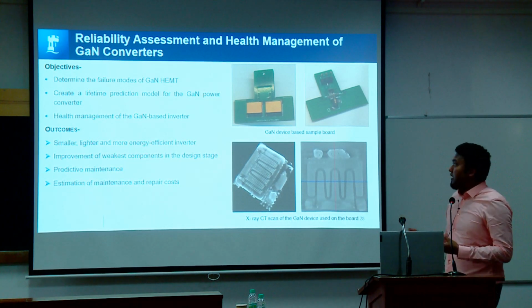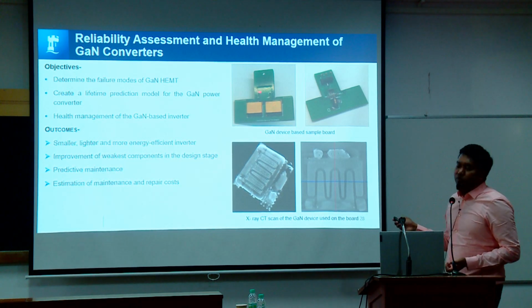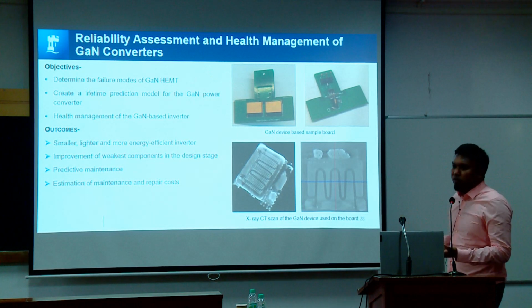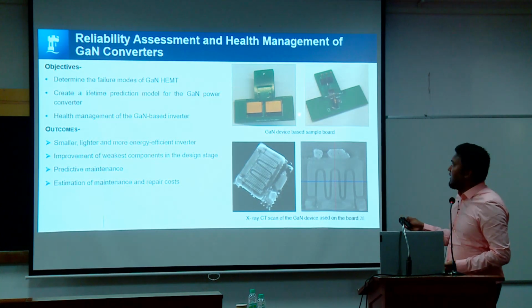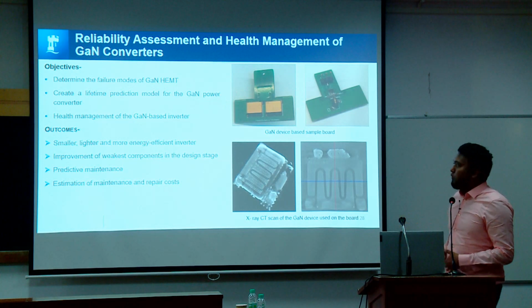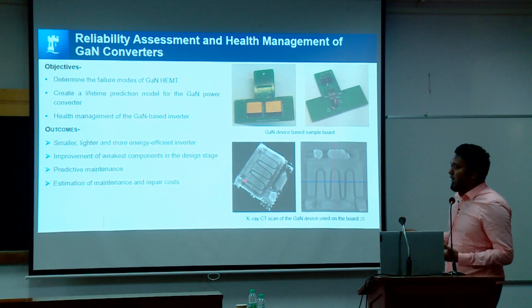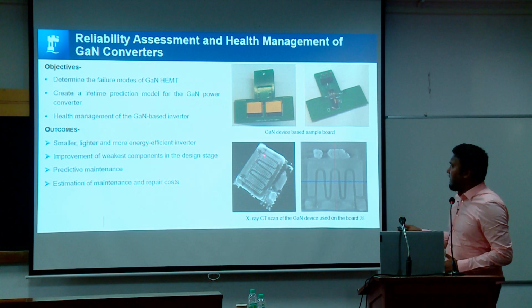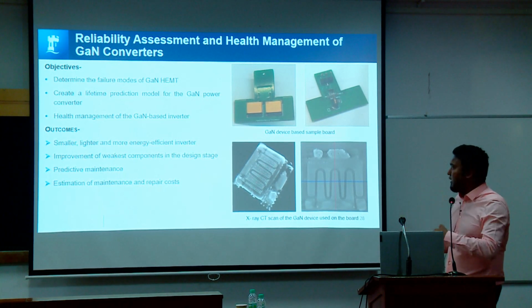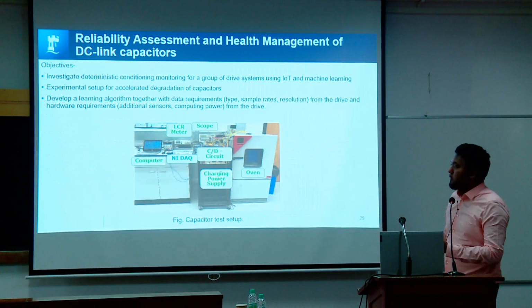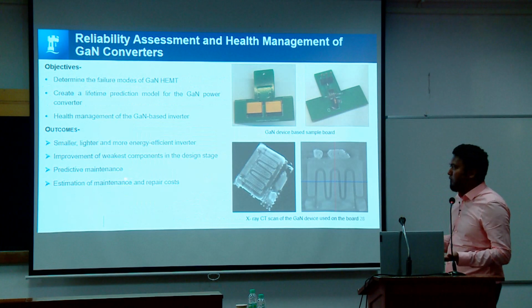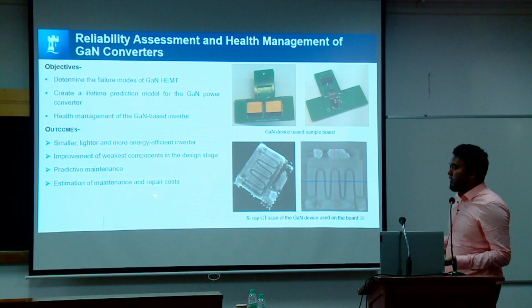So in this case, we run temperature cycling. We don't heat up just the device, we heat up the whole circuit. Then after maybe thousands of cycles, we do 3D X-ray and try to find out if there is any crack in the solder, any crack in the device, or any crack in the copper pillars inside the package. Again, the outcome will be predictive maintenance or estimation of maintenance and repair costs.